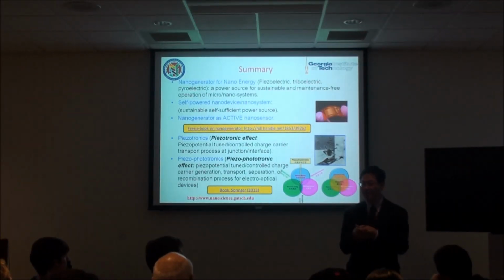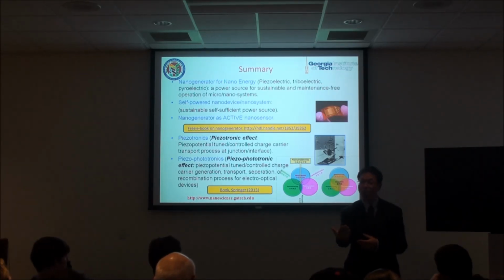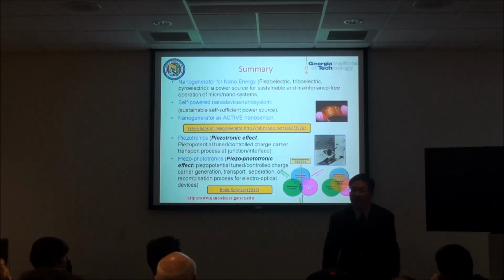The PZT has an outstanding piezoelectric coefficient, so it's outstanding for sensitive transducers. But we use the reverse effect. The power output is proportional to the square of the piezo coefficient, but inversely proportional to the permittivity. The PZT has a large permittivity, so d squared divided by epsilon almost cancels out. In that case, the power output is about the same as zinc oxide.